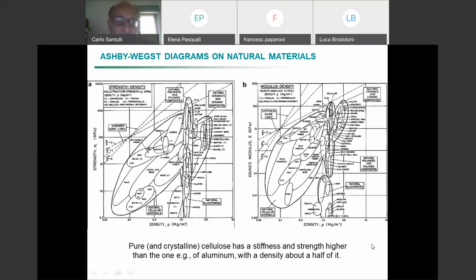The discovery is that we can do this kind of process also with, for example, cellulose. The discovery was that cellulose, in principle, was as stiff, if you can see here, was stiffer or stronger than aluminum, for example. But on the other side, the real cellulose, the one which we know, which is mostly amorphous, which we know in paper and in packaging, we use a lot of cellulose for packaging. Well, it's not as stiff as aluminum, it is way down. So it is all a question of getting it crystalline or amorphous.